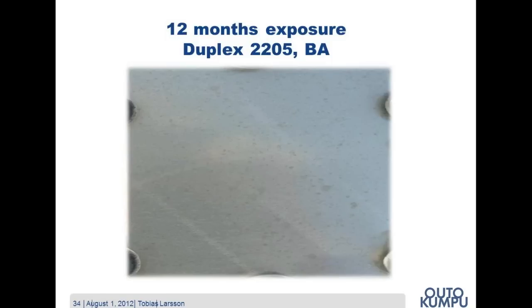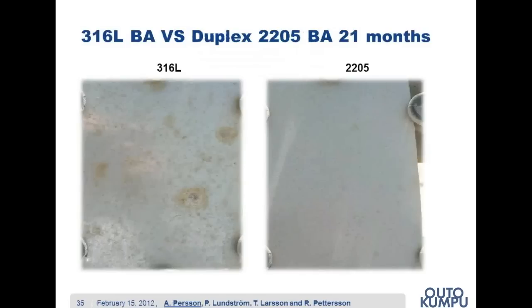Well, even the 2205 with the bright annealed surface finish shows some small staining. However, with a sound cleaning program, this grade would probably be good enough. We should also remember that this is one of the most severe locations in the world, and when we evaluated the first 3 months of our test site or inland, it did not show any staining for the 2205.